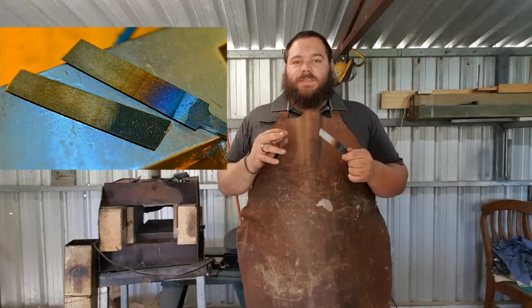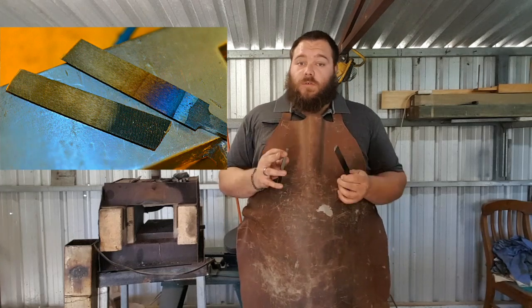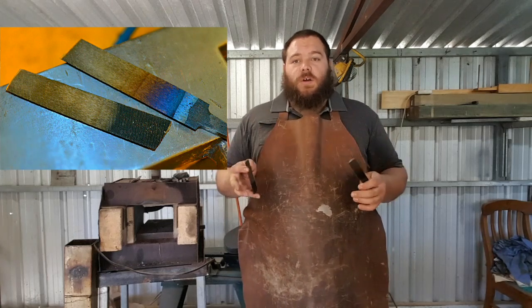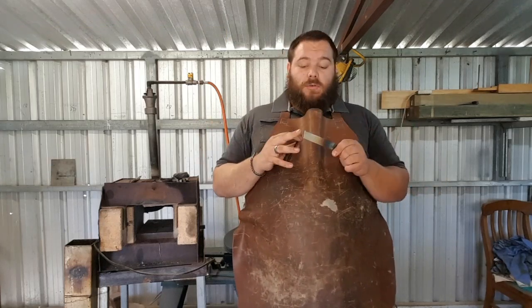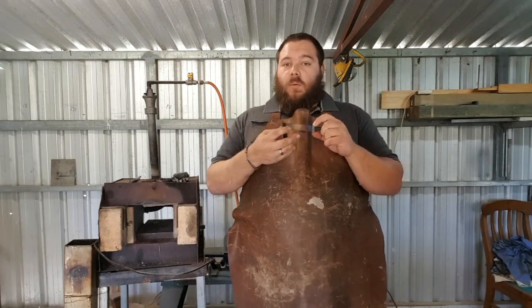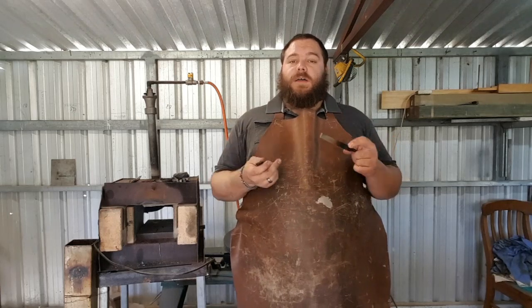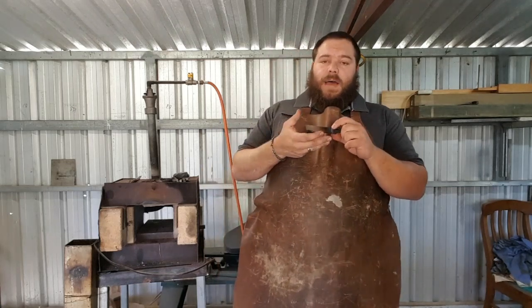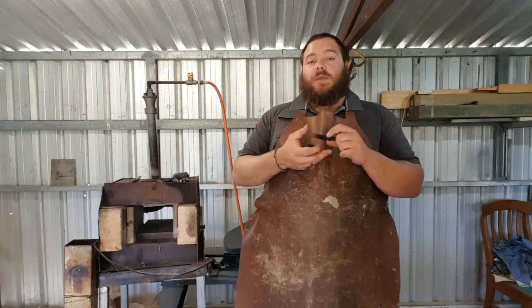Now, that isn't to say that torch tempers don't work. They do work. They've been used historically for centuries effectively, and there's nothing saying that they don't. The only thing about that is, it is normally uneven, especially the torch temper. You tend to have hot spots and cold spots, hot spots being thinner and normally towards the edge, which is normally a very bad thing. And also, they tend to only be on the surface.